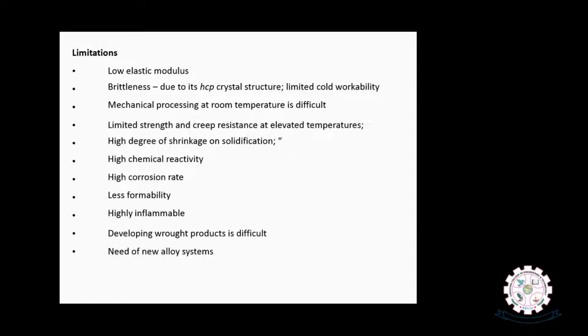So it's low elastic modulus and its brittleness compared with aluminum, and difficulty in mechanical processing at room temperature, and its limited strength and creep resistance at elevated temperatures. With respect to temperature, the ability of magnesium to withstand loads is drastically decreased compared with aluminum. And there is a high degree of shrinkage during solidification when we adopt liquid processing routes, and high chemical reactivity, especially when it is exposed to a corroding environment.